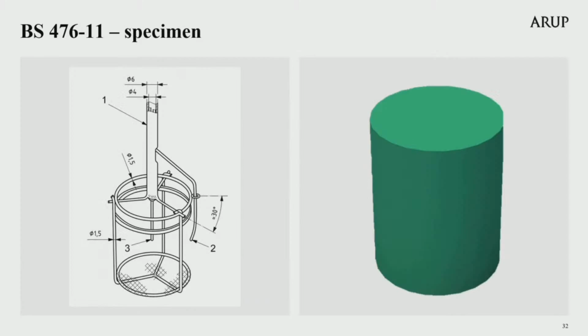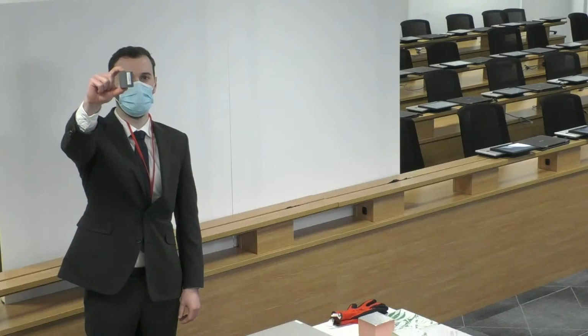The procedure for Part 11 is similar to the non-combustibility test I've just explained, such that temperature measurements and flame observations are also taken. However, the duration of this test can be up to 120 minutes, and the mass of the sample is obtained before the tests. This time 5 specimens must be prepared. Each one a cylinder 45 millimetres in diameter and 50 millimetres in height. My colleague Tom is now showing you an exact replica of a Part 11 test specimen.